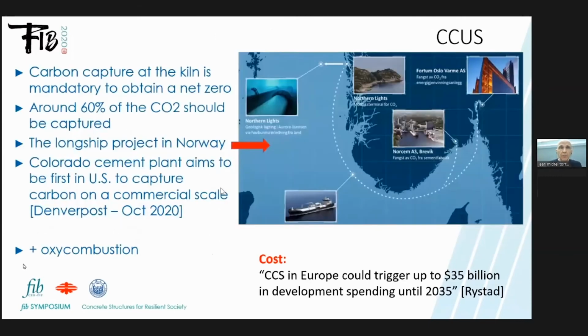If we look at the CO2 impact of cement, it's mandatory, in fact, to use carbon capture at the kiln, because all the solutions I have presented will not be enough to obtain net zero emission. And actually the evaluation is that we need to capture around 60% of the CO2 from the cement factories. And we have some examples of this technology.